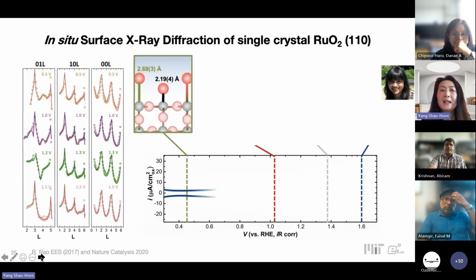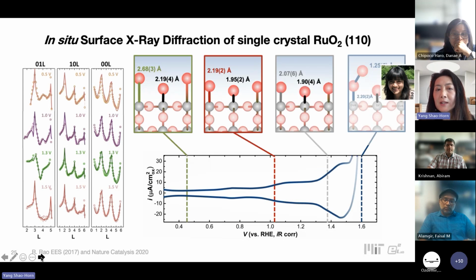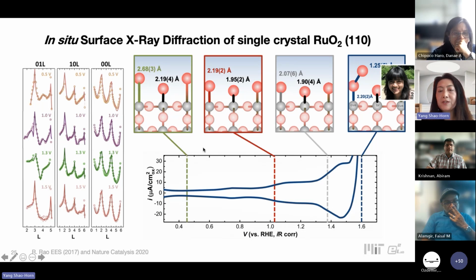So we utilize in situ surface X-ray, really glancing angle X-ray. The X-ray comes in at an extremely shallow angle, so we diffract only the top surface layer, right? We look at the different rods. For example, if you look at the 00L rods that come largely from scattering from ruthenium as a function of voltage of such a single crystal ruthenium dioxide 110, there's no change, as expected. On the other hand, if we look at the 01L or 10L rods, this is coming from scattering largely from the oxygen.